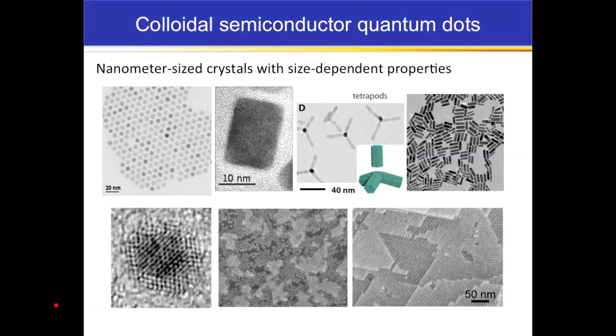For example, this is a core-shell quantum dot where the core is made of lead selenide and the shell is made of cadmium selenide. Because these materials are made colloidally, they're floating around in solution, and so we can use self-assembly to make thin films from them. This is just two different snapshot SEM images of thin films of quantum dots on a silicon surface.